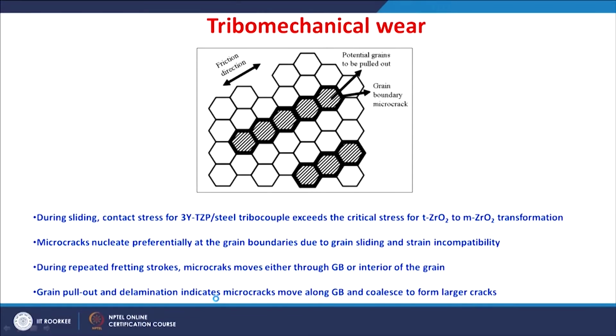So, let us understand this more clearly. What happens during sliding is that the contact stress for this tribocouple exceeds the critical stress that is required for the transformation of the tetragonal to monoclinic zirconia phase.